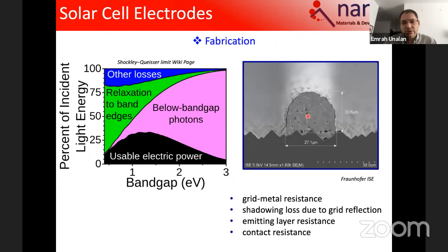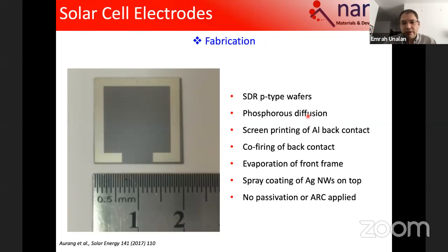So our idea was to use a silver nanowire network on the front surface rather than using the typical finger electrodes. So they have high transmittance. We tested this on a 2 centimeters by 2 centimeters solar cell. And I should assure you that we don't have a passivation layer, so this is not a proper solar cell. So the efficiencies that I'm going to report are going to be low, but the concept is verified. We don't have a passivation layer on this, and we don't have any protection layer on the cell either. So the anti-reflection layer is not there either.